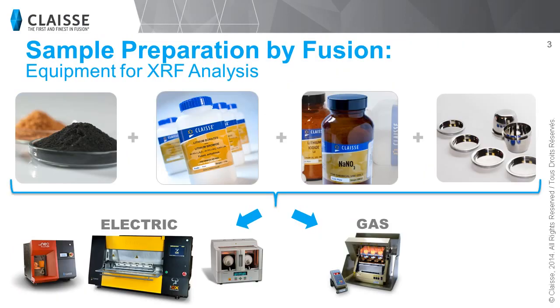Now, what do you need to prepare your samples by Fusion? Here is the most commonly requested equipment. To start, you need borate flux, in which the sample will be dissolved. Depending on the application, you might need other chemicals called additives, such as oxidizers, non-wetting agents, fluidizers, or internal standards. You will also need platinumware. A few different alloys can be used, but the most common is 95% platinum, 5% gold, which is well known for its durability and stability. It is also not wet by the molten mixture during the fusion process.